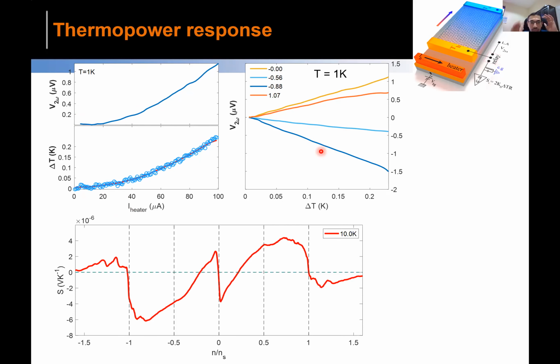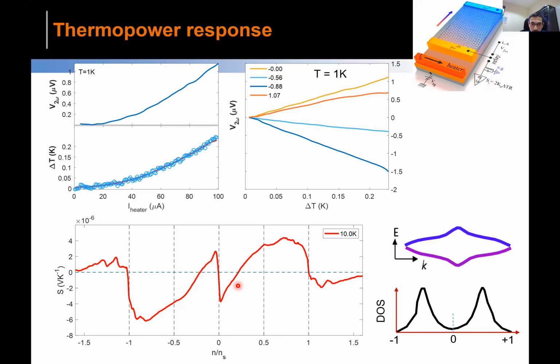So if I do this exercise throughout the band, this is what it looks like at 10 Kelvin. This is what I'm showing here, the Seebeck coefficient in terms of microvolt per Kelvin across the bilayer system. So what I'm talking about here, the zero, again, I say the Dirac point, as I told you, this is a symmetric point. It goes to zero. But there are many interesting, almost like textbook kind of data.